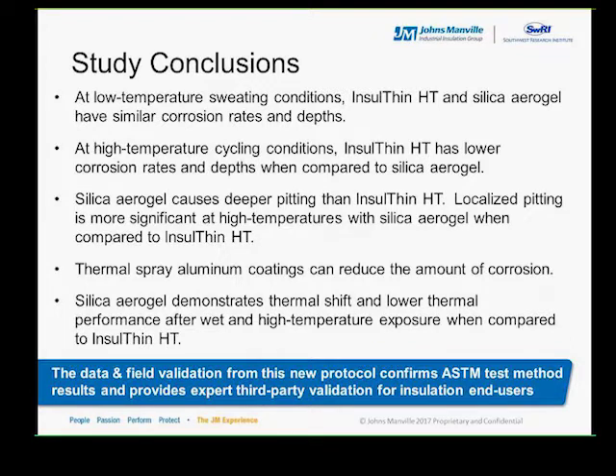So to summarize, the conclusions from this third-party study completed at SwRI are the following. First, at the low temperature sweating conditions, InsulThin HT and silica aerogels have similar corrosion rates and depths, and this was seen in both the electrochemical and ultrasonic test methods. At high temperature cycling conditions, InsulThin HT has a lower corrosion rate and depth compared to silica aerogels, and more importantly, the silica aerogel causes deeper localized pitting, which again is very significant from a failure analysis standpoint compared to a uniform surface corrosion.